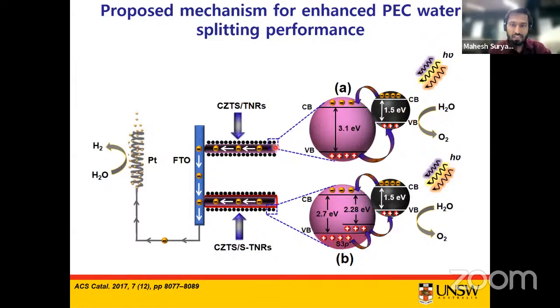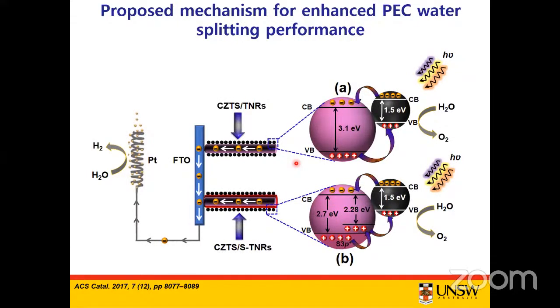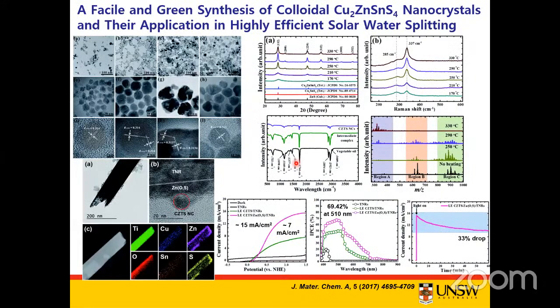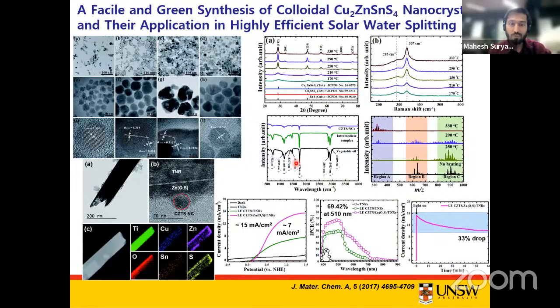Based on this, we can simply say that this sulfur doping as well as the CZTS sensitization synergistically lower the charge recombination rate of these photogenerated electron-hole pairs, and thus facilitate the participation of more charge carriers in solar water oxidation, and significantly enhance the solar water splitting performance of these TiO2 nanorod arrays.